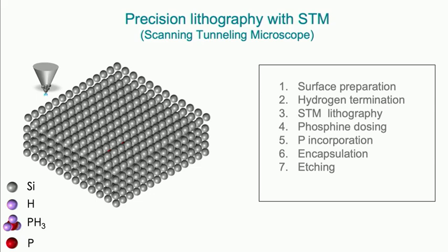And so in this way, you can build almost atomically precise qubits or wires or control structures all on that plane, and do that with almost atomic precision. You don't have quite atomic precision because you opened a patch and you're not sure exactly which lattice site the phosphorus donor went into, but pretty close. And finally, of course, we can then use conventional electronics with wire gates to connect down from the surface to those buried structures that you've fabricated.